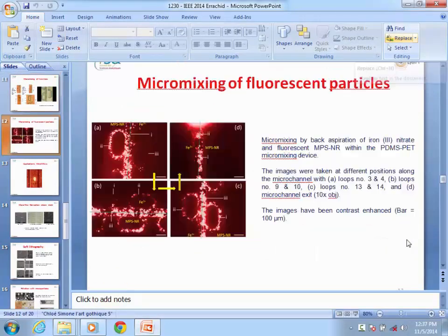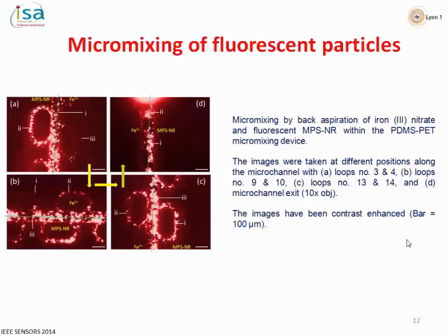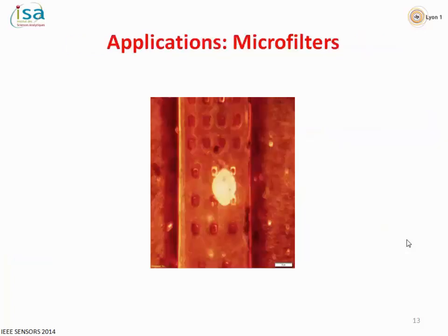Well, and after that, we start to increase the degree of difficulty. That means we start to inject other things, like magnetic particles labeled with fluorescence in order to see if we are able to mix all together. And we can see clearly here at the beginning and at the end, and we can see we fill all these loops in less than 5 minutes. Let's talk about the second part, filter.